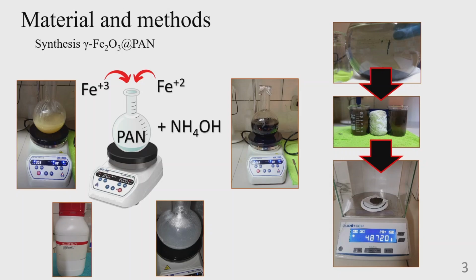With N2 flux bubbling through the reaction, the resultant ultrafine magnetic particles were treated by magnetic separation, washed several times with ultrapure water, and then redispersed into a suspension with 50 millimolar and pH 7. The oxidation of the magnetite into maghemite was achieved by lowering the pH value to 3 by adding hydrochloric acid, 37% purity, at about 80 centigrade for 30 minutes. The stirring rate was kept constant during the whole oxidation process. The sample was dried at 60 centigrade, resulting in a reddish brown powder.